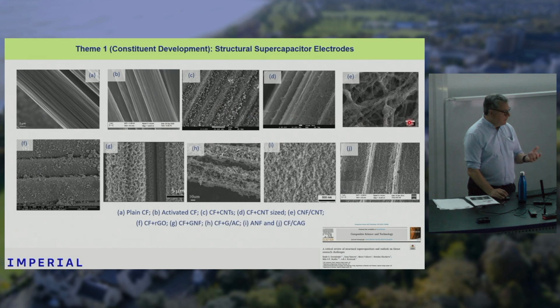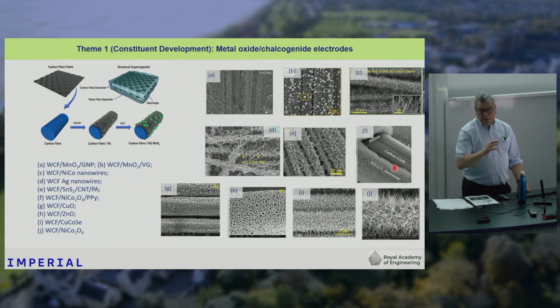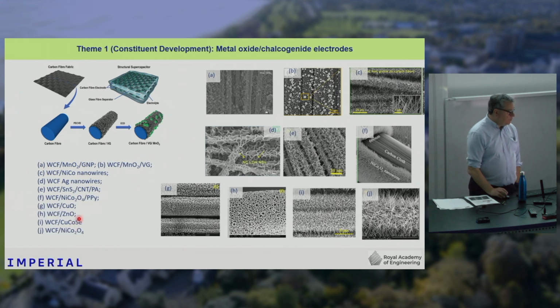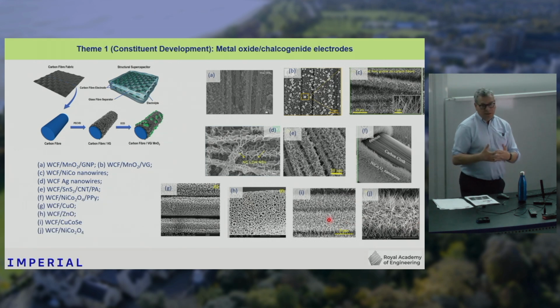You can grow nanotubes on the surface, you can put graphene on there, people are putting graphene onto aramid fibers and things like that. What we focused on is carbon aerogel as a route for doing this, and I'll talk about that in a minute. The other route is to introduce a little bit of chemistry in there, so you get some battery chemistry, and this is known as pseudocapacitance. There are various different types of material. Manganese dioxide is the commonest used material to induce some degree of chemistry, but there's a lot of work looking at copper oxide, zinc oxide, and these chalcogenides. These are selenium-based compounds which offer pseudocapacitance. The idea is that you grow this active material onto the fibers, so that increases its capacitance. But if you get interlocking between these spikes, that's going to give you improved mechanical properties as well. So that's something we're exploring with this technology.